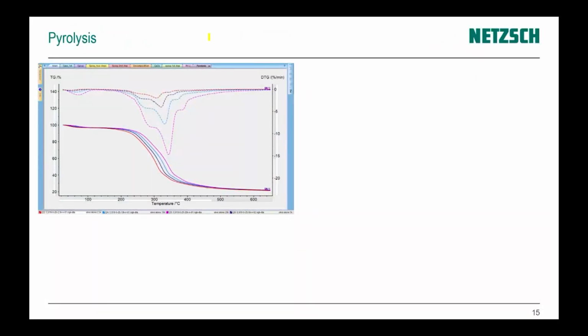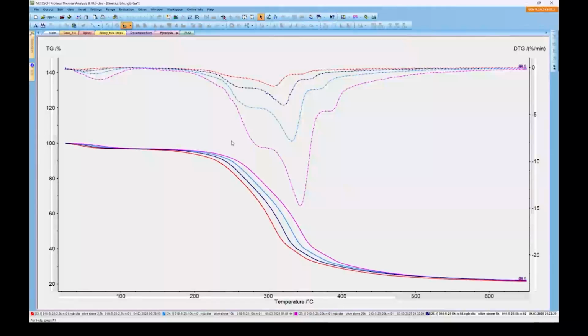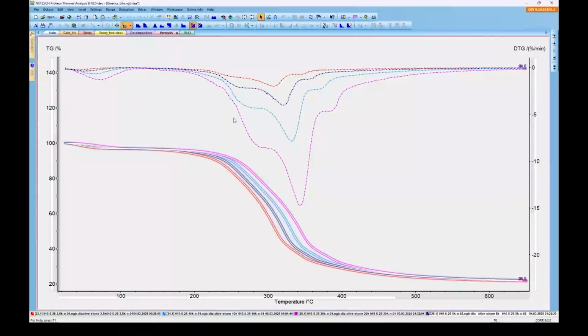Next example, pyrolysis. Here is a really complex thing. We have water release. We have decomposition of hemicellulose, of cellulose, and at the end we have lignin. So this is really a lot of different peaks. Here we have decomposition of olive stones. And let's go to our data. Here, pyrolysis. We have our TG data and we have our DTG data, the first derivative.